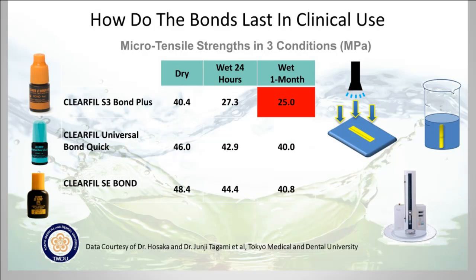And so how do the bonds last in clinical use? This is a microtensile study. What they did was they took a mold, put the bonding agent in it, then popped it out of this flexible mold and put it in this machine and broke it. That's the first column over here. Then for the second column, they put it in water in a beaker for 24 hours, and then they put it in here and broke it. And so that's tensile strength, pulling it apart.